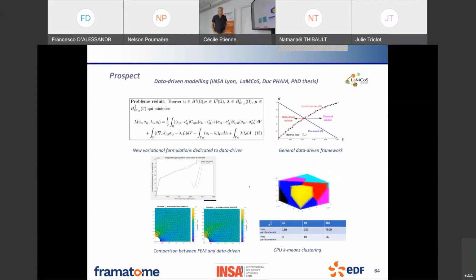Here is the first example. It is another way to show the same idea here. It is on the right a general data-driven framework, which is a compromise between a set of partial derivative equations physically based, which corresponds to the blue line, and the black points correspond to the data experiments. And so instead of trying to identify a constitutive law physically based in red, we only focus on the black points in order to build a compromise between the governing equation and the experimental data, which is at the end the data-driven solution, and it can be compared to the classical solution in a finite element framework, for instance, based on constitutive law, standard constitutive law.